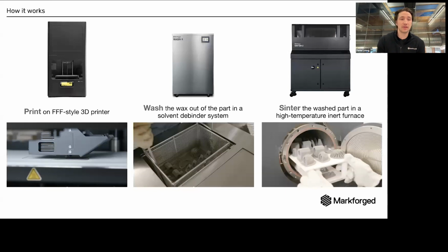The printer itself is essentially a highly specialized FFF printer that's designed specifically to print this polymer. It turns out that this polymer is not as amenable to 3D printing as, say, PLA or nylon or Onyx, our filaments. So it's a tricky polymer to print. It's a highly specialized machine. It has a heated chamber, heated bed, and we print it. And when we print it, we scale it up about 20%. The reason we do that, I'll get to in a second.